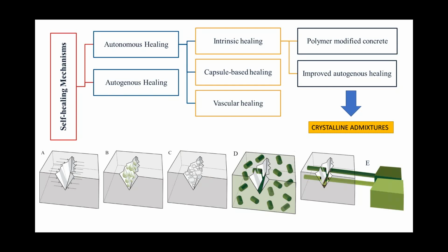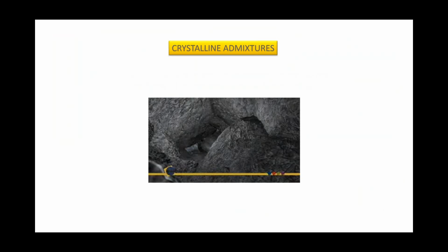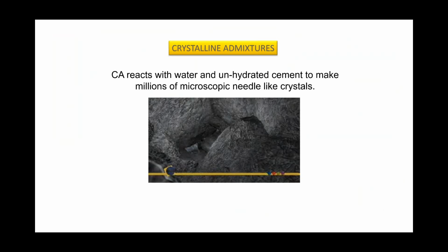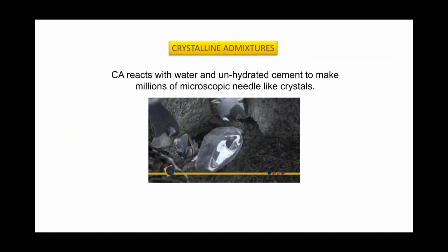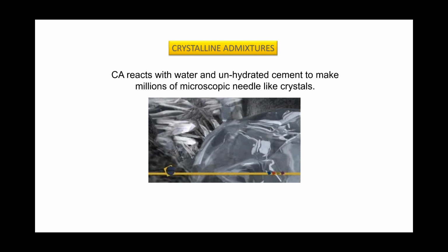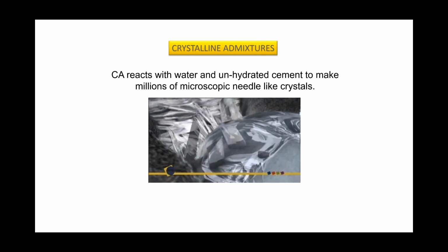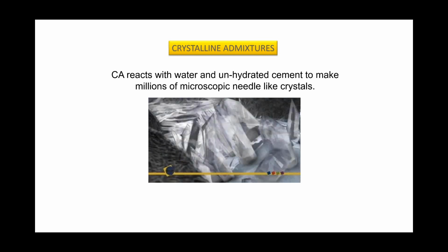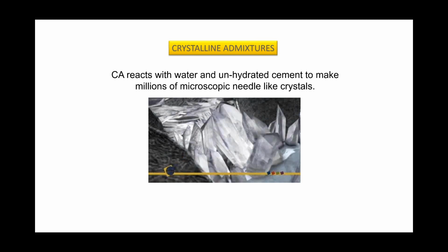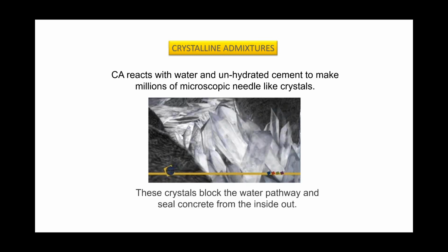So I'm working on a technology called crystalline admixtures. These crystallines are hydrophilic materials which have a tendency to react with the water and un-hydrated cement to make millions of microscopic needle-shaped crystals. As you can see in the animation, this crystal is going to form inside the crack, block the water pathway, and seal the concrete from the inside out. And this admixture is typically added during construction.